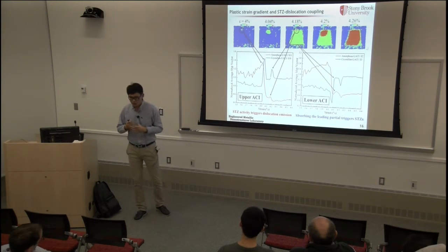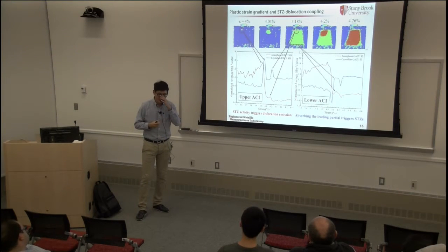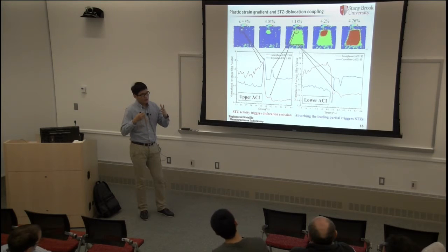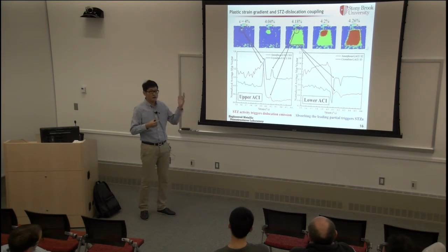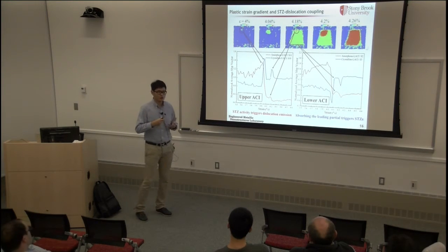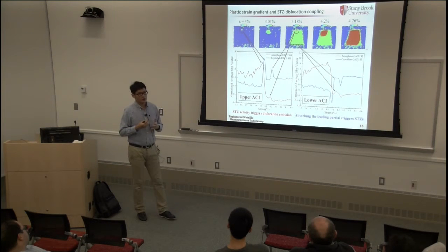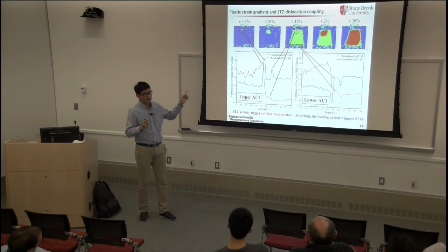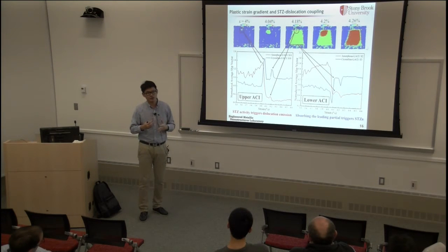Another reason is that metallic glasses are characterized by a lot of free volume, which means the material is less dense than the crystalline form. There will be more free volume in the amorphous layer, which could migrate to the interfaces and then trigger the dislocation emission from there. So we can use these two different views to study this interfacial dislocation emission process.